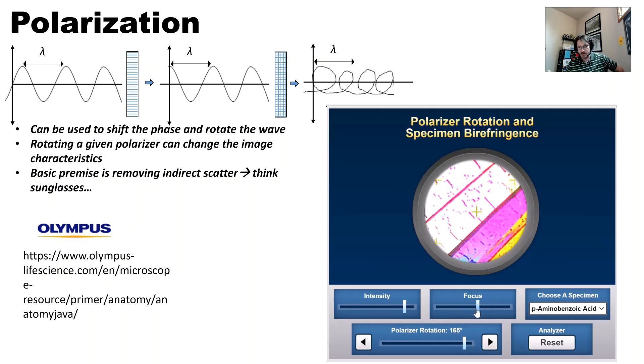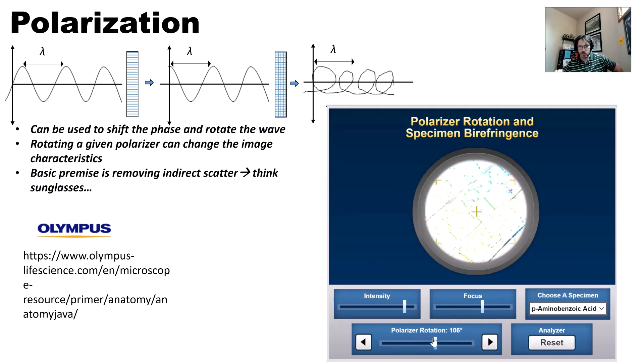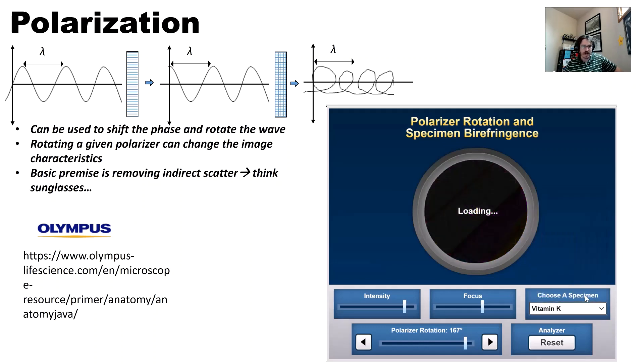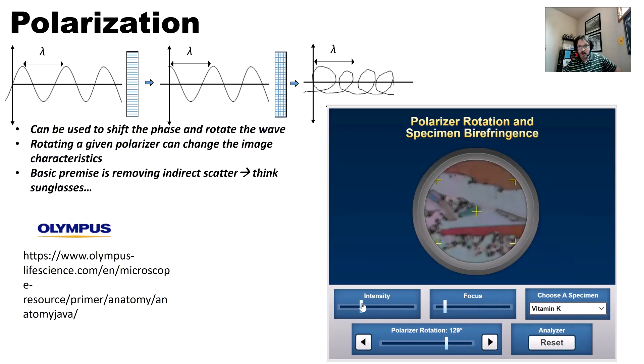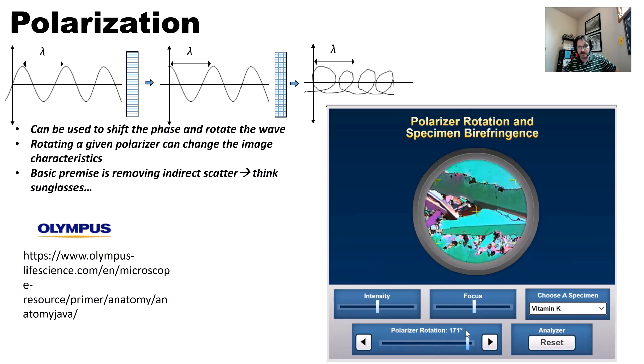You can change the intensity of light - if you put in too much light it gets blurry so you have to adjust your focus. These are very good tutorials. If you rotate your polarizer you're changing what you see - changing how the light is interacting with the sample. In metallography you can use a polarizer to determine if you have inclusions; sulfide inclusions tend to glow under the influence of a polarizer.